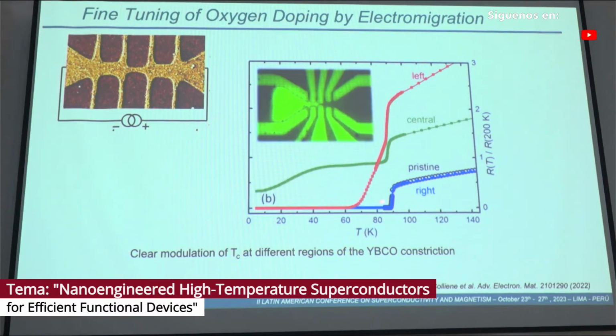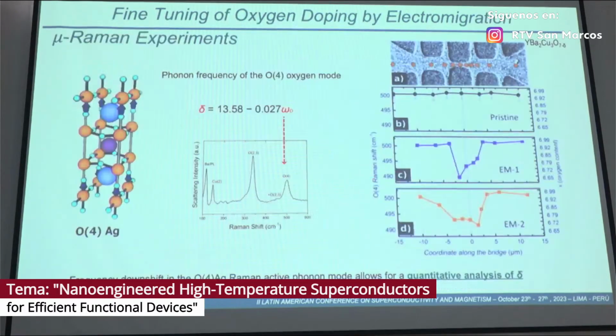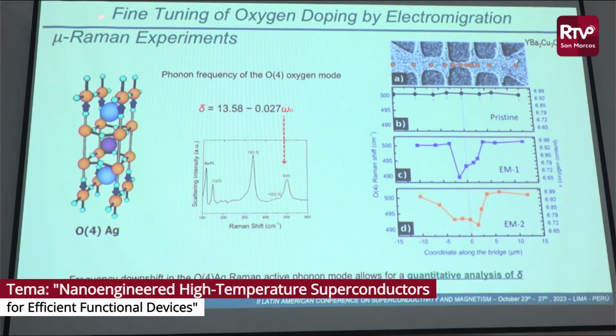Starting from the pristine state, we can introduce or reduce the oxygen and drive the system to the insulating state, by applying current in one direction. And in order to track the change that we introduce in the oxygen, what we use is the micro-Raman experiments. With the Raman spectra, one can track the delta value of the oxygen content in the system by exploring the vibration of this oxygen here.